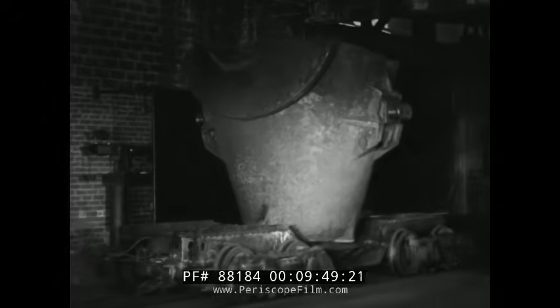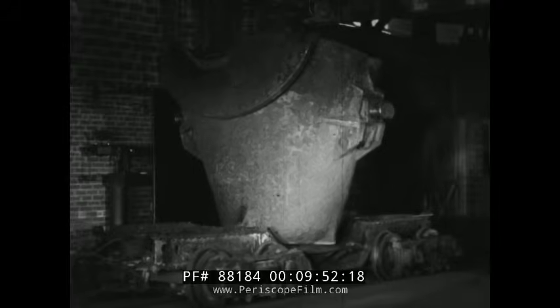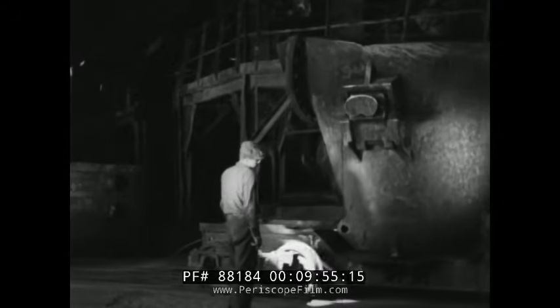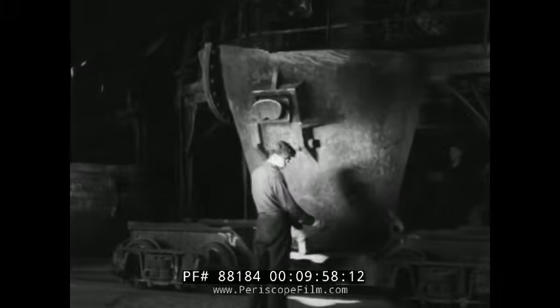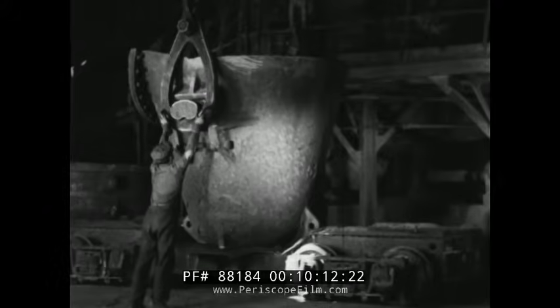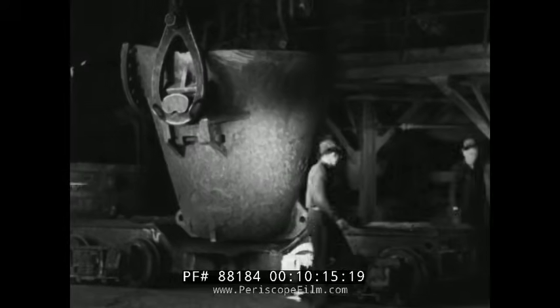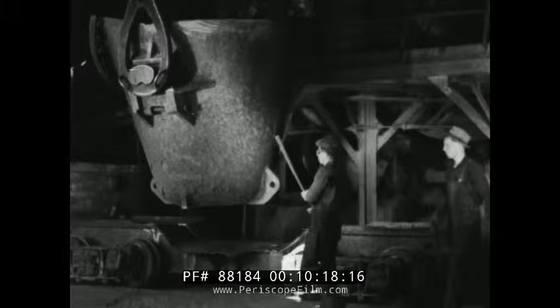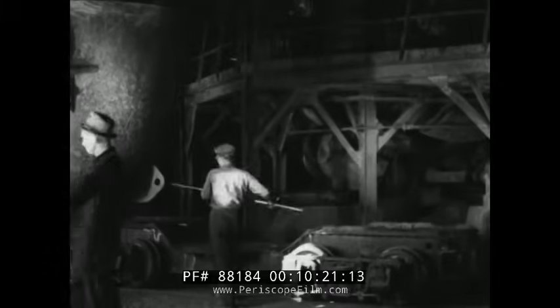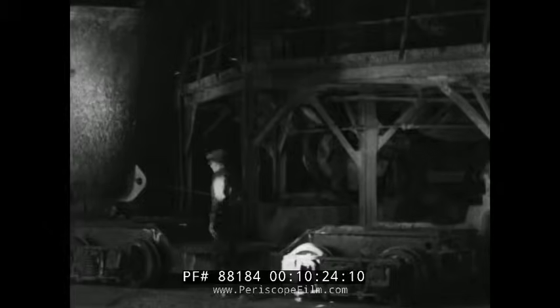The molten matte from the converters is poured into a huge ladle and placed on the transfer line, which under electric control pulls the car into the Orford department. In this process, sodium sulfate is added and also some cold matte to control the temperature. Here it is picked up by a 50-ton crane and carried to a basic converter. The molten mix is allowed to stand while a primary separation takes place. The copper sodium sulfide is later taken to the acid converters, and the heavy nickel sodium sulfide goes to the cupola furnace.